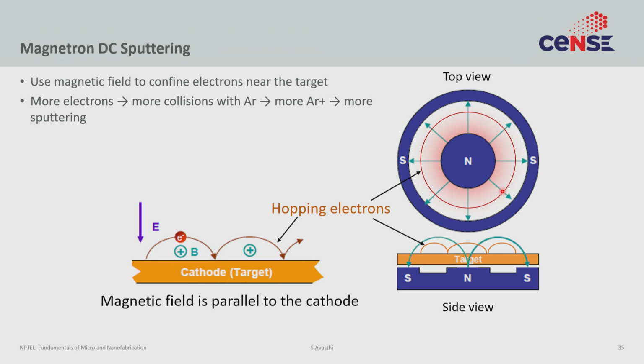Now, this would have been the end of the matter, except people are smart. So, somebody came up with the idea of using a magnet to enhance or change this optimization. So, the basic idea is simple. If you attach a magnet, it affects charged particles in a very predictable fashion, which is that charged particles tend to go in spiral or circular paths in a magnetic field. So, using that, what you can actually do is make the plasma inside the chamber non-uniform.